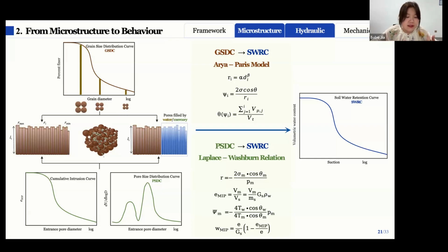The basic idea is that we assume that the soil can be represented by an equivalent bundle of capillary tubes. And in this way, particle size is related to the pore size. And then using capillary theory, we can estimate the suction and reconstruct the SWRC from the grain size distribution.